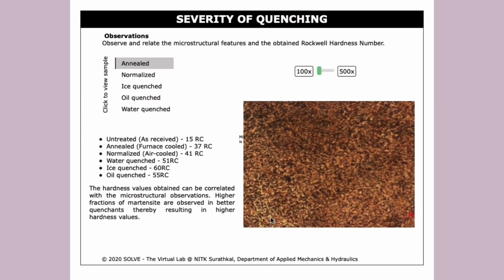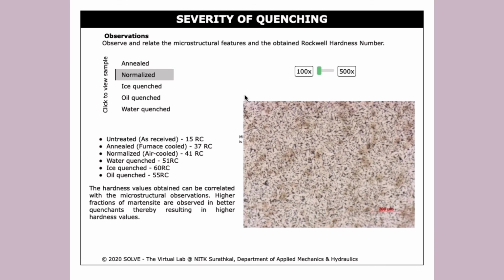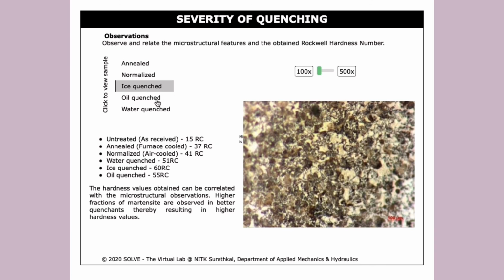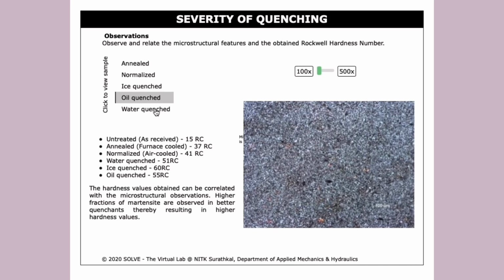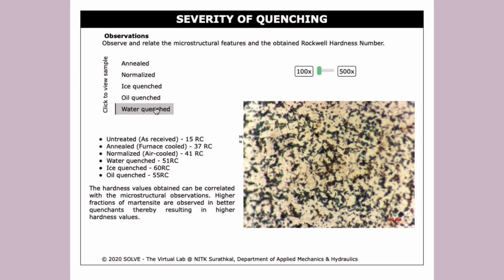In the end, we are required to observe and relate the microstructural features and the obtained Rockwell hardness number. We will get a better visualization as we zoom in on the sample microstructural features. So this is the annealed microstructure feature. This is the normalized, ice quench, oil quench and water quench microstructure features.